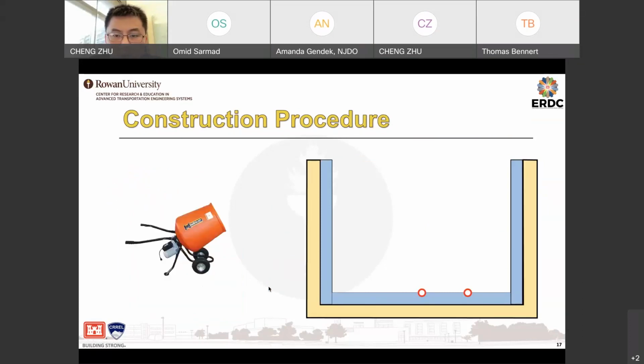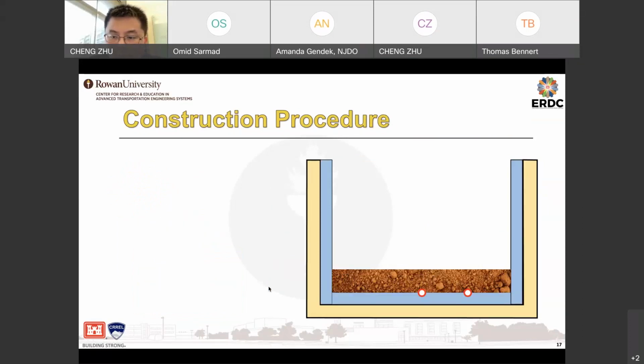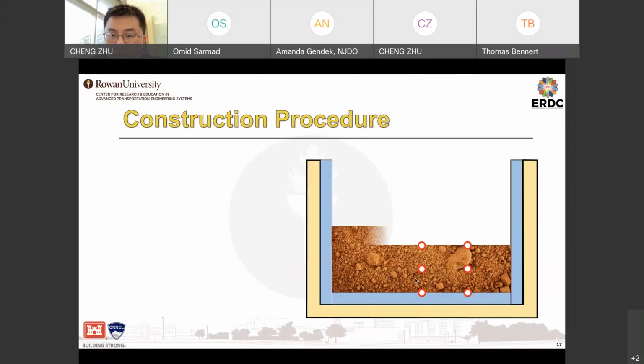Next, we mix the sample and compact the sample into different layers. We compact the sample and make multiple layers for the subgrade, and we use this gauge to measure the density, to make sure the density and water content satisfy our expectations. So we repeat this process for multiple layers, and that's how we prepare the subgrade layer.